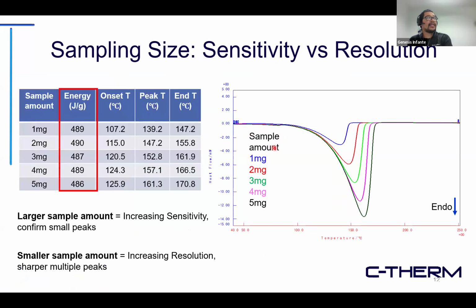And another important factor is sampling size. So here is an example with the same DSC conditions, heating rate, and temperature range, but with different amounts. You can see that the intensity and the resolution are different with higher amounts, meaning a slight shift to a higher temperature in terms of the onset temperature, the peak temperature, and the end temperature. However, because the energy is normalized against the mass of your sample, when you integrate the area under the curve, you can see that it's practically identical.